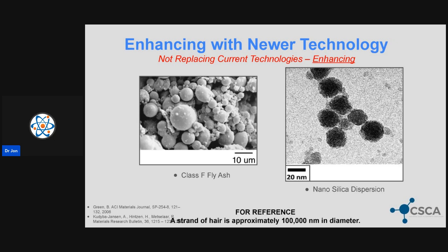As a reference, a human hair, obviously not on my head, is around 100,000 nanometers in diameter. For my concrete folks, on the left-hand side, our fly ash that we traditionally use, that poor man's water reducer with a pozzolanic reaction, under an electron microscope we'll see somewhere between 1 micrometer and 100 micrometers. Here we see it around 10 to 20 micrometers in diameter. Using a similar electron microscope, when we look at nano silica, it's around 10 to 20 nanometers, effectively 1,000 times smaller than our fly ash.